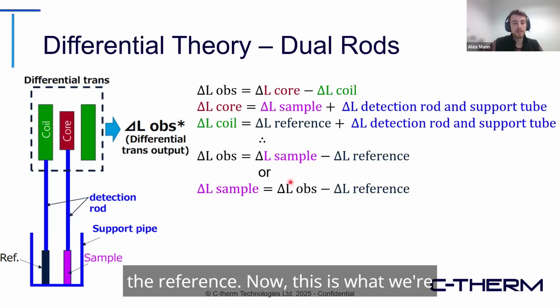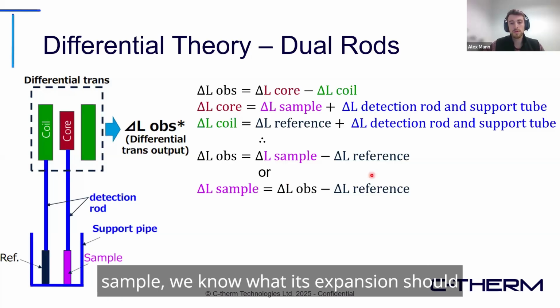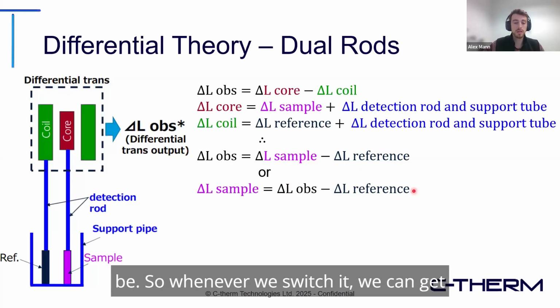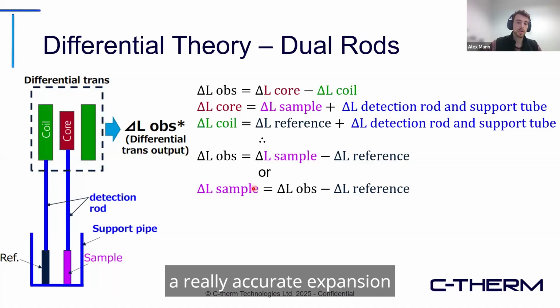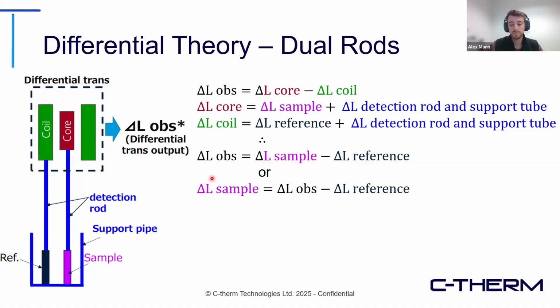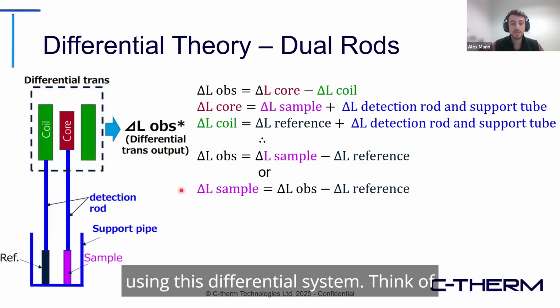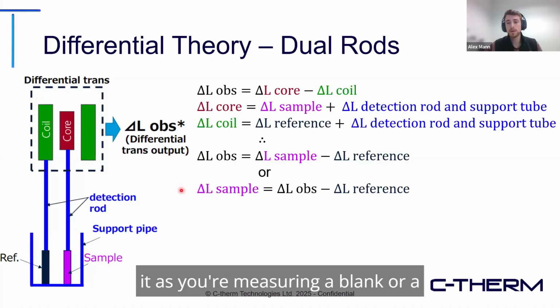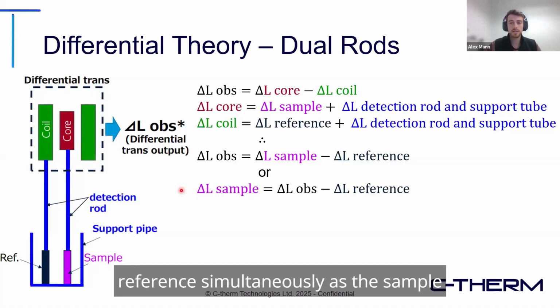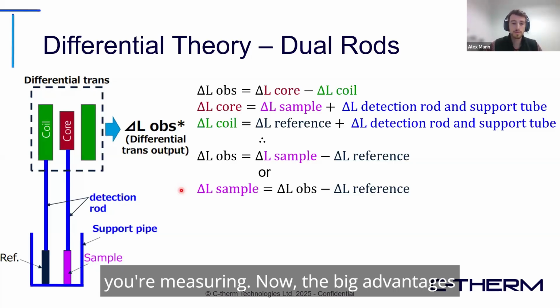Now, this is what we're measuring, and because it's a reference sample, we know what its expansion should be. So whenever we switch it, we can get a really accurate expansion using this differential system. Think of it as you're measuring a blank or a reference simultaneously as the sample you're measuring.